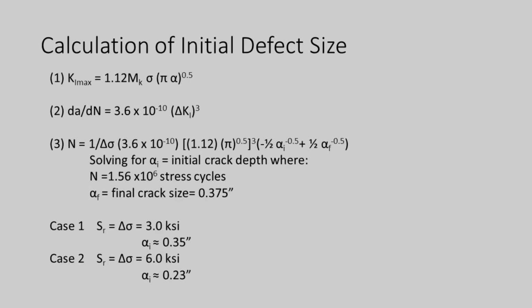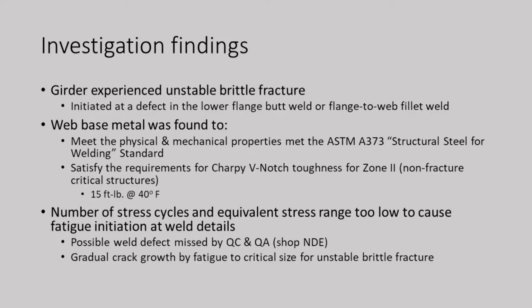We had several stress ranges we wanted to look at. The typical stress range when we did all these bridges back in the 90s was about 3 KSI per cycle, equivalent Miner stress. And if we plug that into the equation with the rest of these numbers, we figured out that the initial crack size was only about 0.35 inches. And then for the larger stress range, we find that the initial crack size should be about 1/4 of an inch, 1/4 to almost the final fracture size. And those are flaw sizes that any NDT operation in a fab shop using radiography or ultrasonic testing should pretty easily detect.